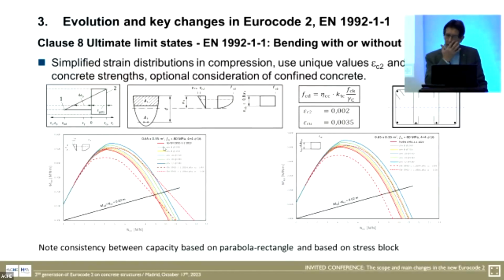Clause 8, ultimate limit state, a few words about bending with and without axial force. Here we have first of all simplified the strain distributions in compression. We now allow for all these compression states to reach epsilon_cu. We also give just unique values for epsilon_c2 and epsilon_cu, the ultimate strain of concrete, identical values for all strength classes. So this should, in my opinion, simplify the design. And why could we do that? Because we have now considered the increased brittleness of the higher strength concrete on the strength side. So not on the strain side anymore, but on the stress side.